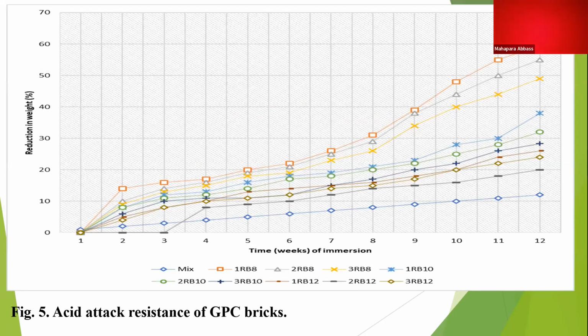Now coming to the acid attack, here we are looking at the weight loss of the specimens. The specimens were immersed in HCl solution for 12 weeks, and after every week the 1% HCl solution was changed and the specimens were weighed, and then the weight loss was found out for 12 weeks. What we have seen is that 2Rb12 had lesser weight loss as compared to all other mixes for the first 3 weeks, but mixes 3Rb12 and 1Rb8 had a lot of weight loss in the 1% HCl solution.